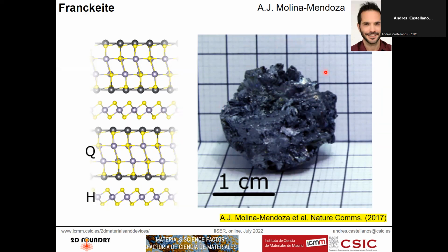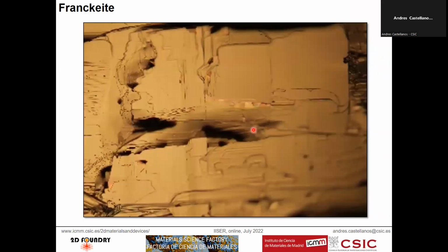But the rock looks like this, as ugly as this. I mean, nothing to do with graphite, nothing to do with molybdenite, so really ugly. But when you take a microscope and zoom in, you see that indeed the surface makes these kinds of long terraces. So it means that with this kind of structure, one can think of exfoliating the material. It's not crazy to exfoliate this. So we started to exfoliate this Franckeite.